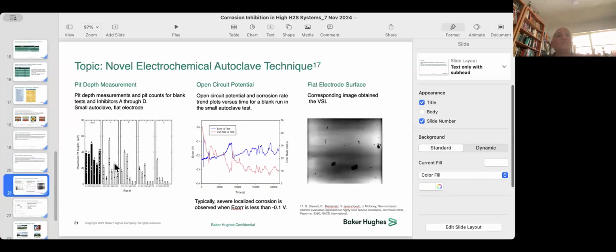One way of doing it is simply you put your coupons in, you take them out after, it could be 7-day tests. We also developed an electrochemical technique, and what this technique was is the following. Whenever pitting occurs, normally your system is at galvanic equilibrium. In our CO2 systems, they're just above the iron to iron 2 plus on the galvanic series. If you see a big bump in potential, that's what we think is the initiation of a pitting event.